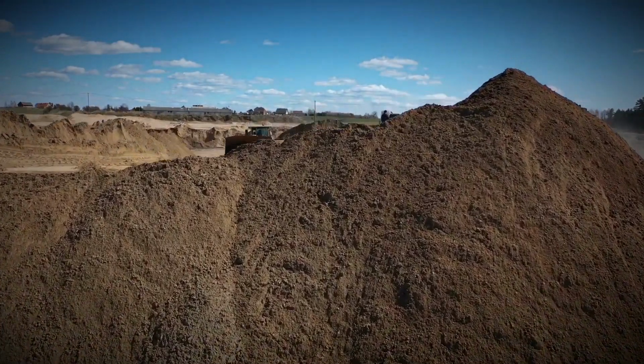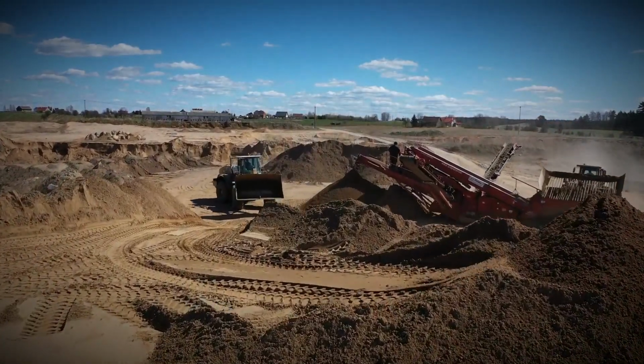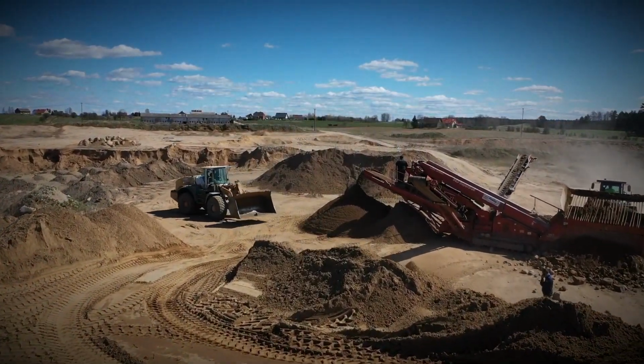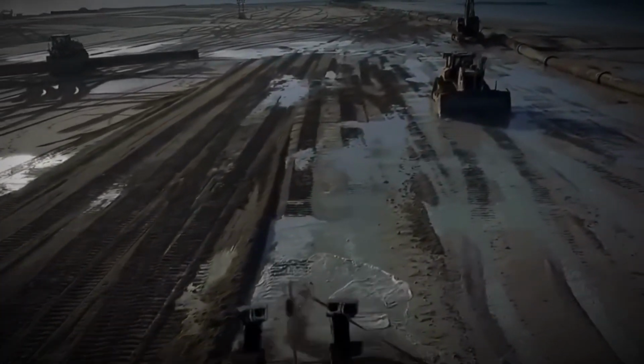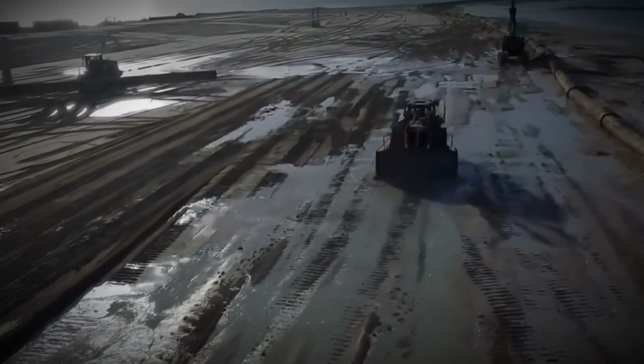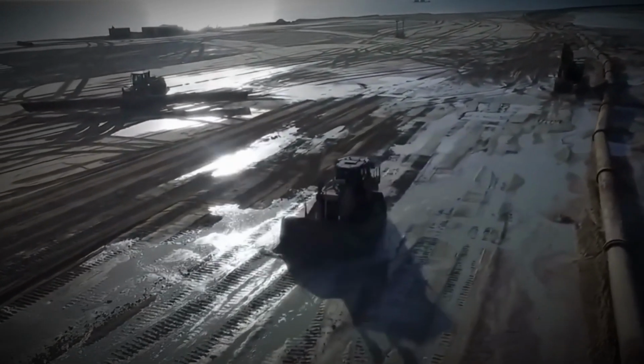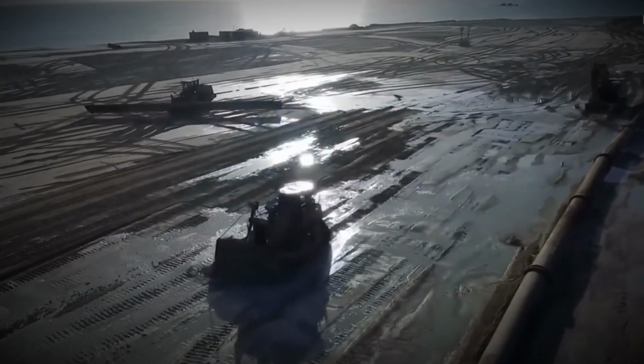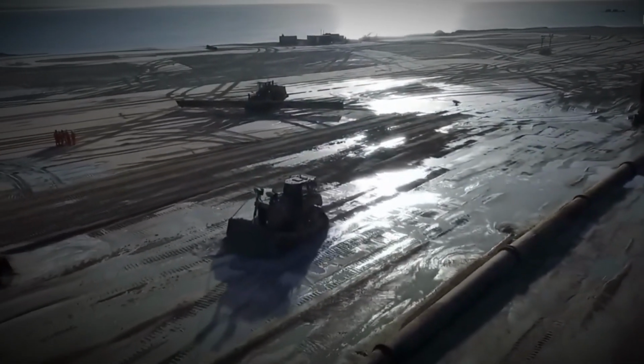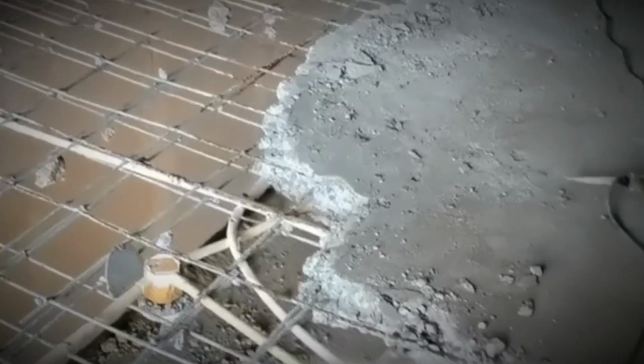Sea sand is smooth, which is bad for bonding, but more importantly, it is full of salt, chloride. If you don't wash the sand thoroughly, which costs time and millions of gallons of fresh water, that salt gets into the concrete mix. This triggers a chemical catastrophe called chloride attack. Chloride ions penetrate the protective passivation layer of the steel rebar. This causes the steel to rust at an accelerated rate.